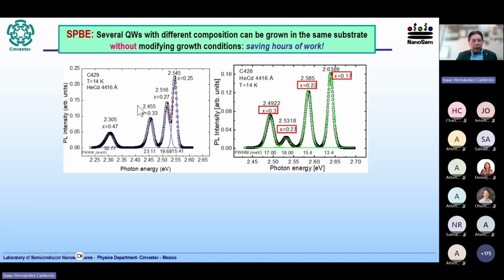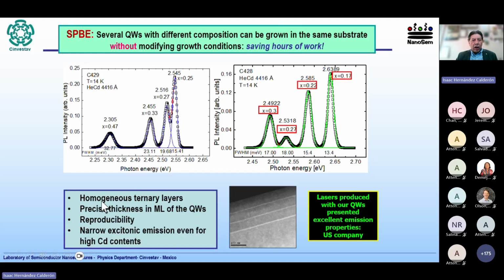This is very interesting because then we can tune the emission in different colors, for example, for their application in LEDs and lasers. And we have additionally the possibility to improve the quality of these materials because they are very homogeneous. Since we grow in a layer by layer mode, we can have a precise thickness of the quantum wells. We have high reproducibility. We have narrow exciton emission, even for high cadmium contents.